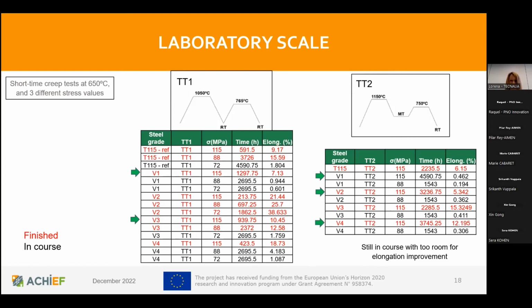In red, those that have been finished. In black, those that are still in course with still room for elongation improvement. And there is another set of tests that have not been started yet. Okay, so if we focus on the highest stress values, first of all, on the creep tests that are finished or almost finished, and then we take into account those that are processed at higher stress values. In case of thermal treatment 1, we can say that the samples that show the best behavior are V1 and V3.